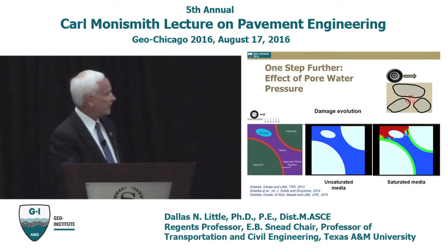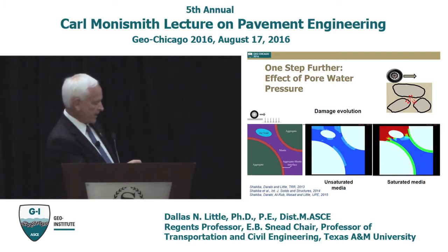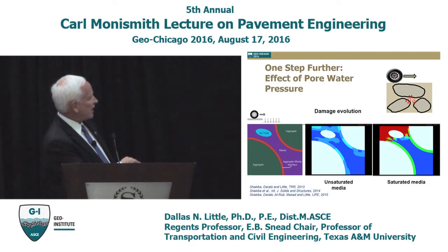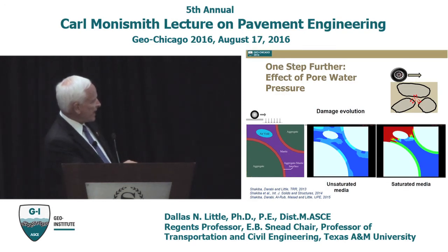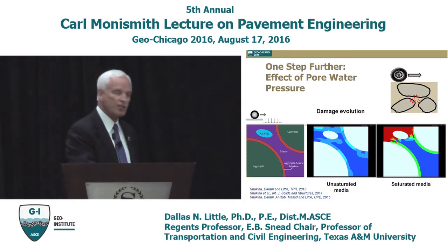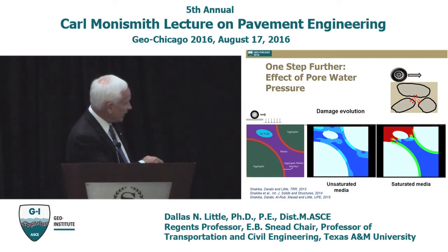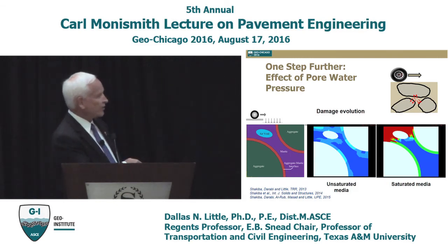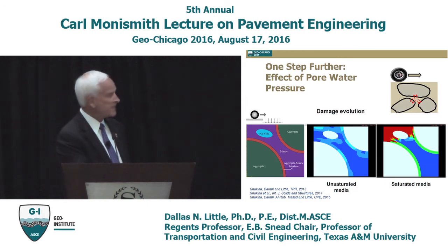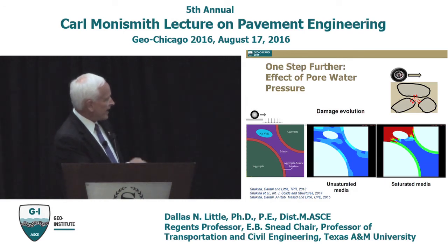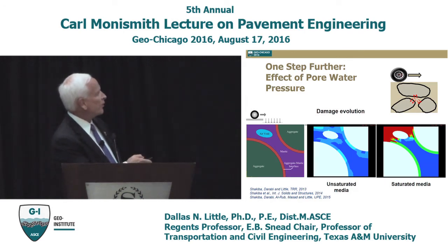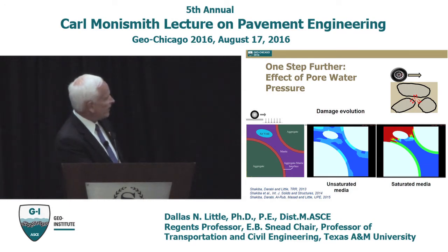Let's say, and my animation's getting a little bit ahead of me here, but let's say that we're going to model something very simple. We've got an aggregate particle. We've got the blue mastic, another aggregate particle, the red interface, which is where the adhesion occurs, and we've got an air void here. So that air void is now filled with water. It's saturated, and we're allowing diffusion to occur. If we apply a load to this material, and I'll try to back up.